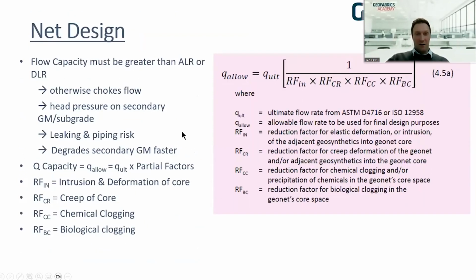In terms of net design, look, this might get a bit technical, but I'll run through it as best I can. So the flow capacity of a net must be greater than the leakage rate or your action leakage rate that you've set for that asset. Otherwise, if it can't handle the flow rates, it'll choke the flow and you'll get head pressures on your subgrade or your secondary liner, and then that will risk leaking or going into your embankment. So you're really trying to keep, your net has to keep up with the leaks that you're expecting.